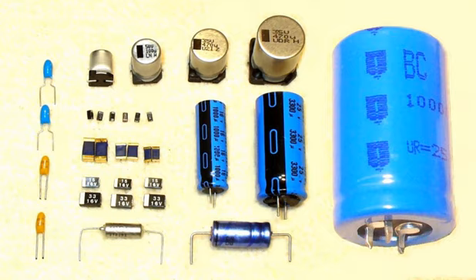with polymer electrolytes. For non-solid aluminum electrolytic capacitors, the leakage current includes all weakened imperfections of the dielectric caused by unwanted chemical processes taking place during the time without applied voltage, the storage time between operating cycles. These unwanted chemical processes depend on the kind of electrolyte. Electrolytes with water content or water-based electrolytes are more aggressive to the aluminum oxide layer than are electrolytes based on organic liquids. This is why different electrolytic capacitor series specify different storage times without reforming instructions.